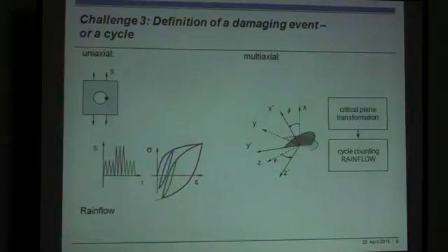Cycle identification in the plane under investigation. I forgot to mention that all these things are strictly plane-related algorithms. So all that is calculated now with respect to crack growth is not done in one direction only. We have to search, and we have to introduce a 5 degree or so step going through the calculation and repeat it, and then at the very end figure out which life was the shortest.